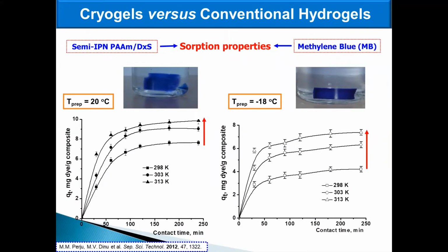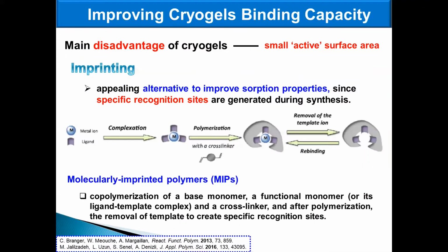The ionic composite hydrogels based on polyacrylamide were tested as sorbents for methylene blue from aqueous solution. The absorption capacity was dependent on the gel structure and the temperature at which the sorption was performed. As expected, the absorption capacity increased with the increase of temperature, but conventional hydrogels showed a better absorption because they exhibit a higher surface area and more ionic groups available to interact with the cationic dye. So, the main disadvantage of cryogels is their small active surface area.